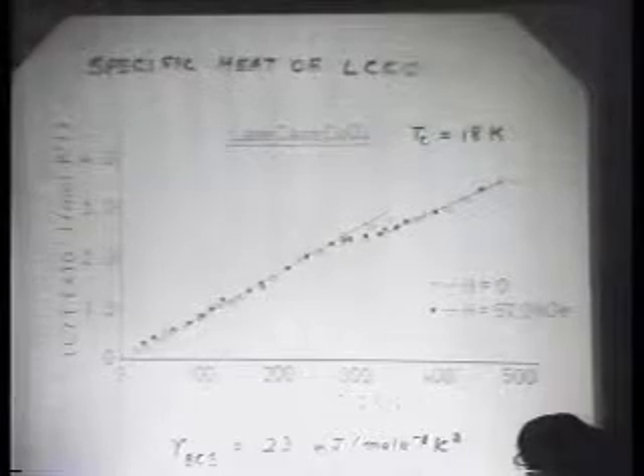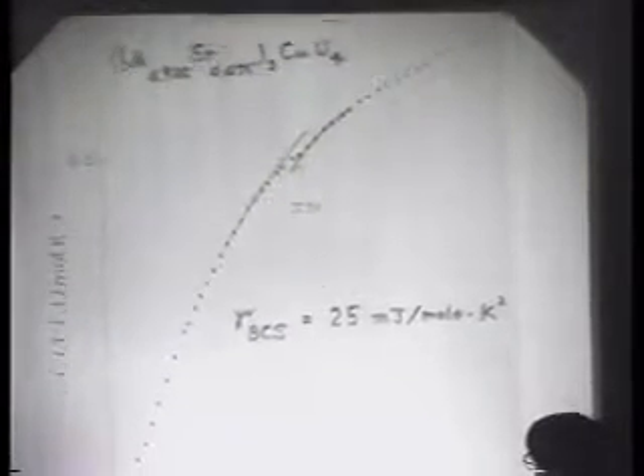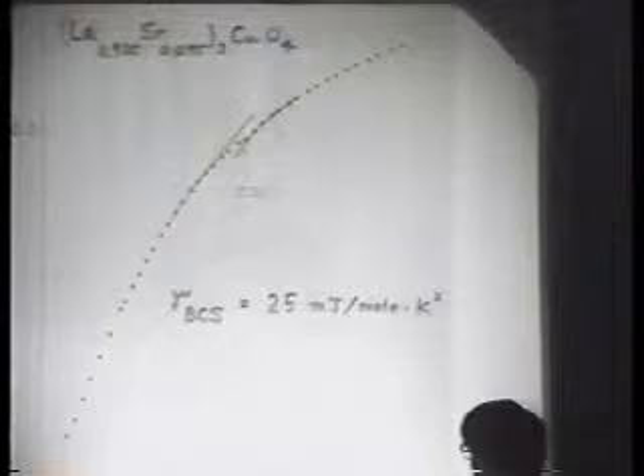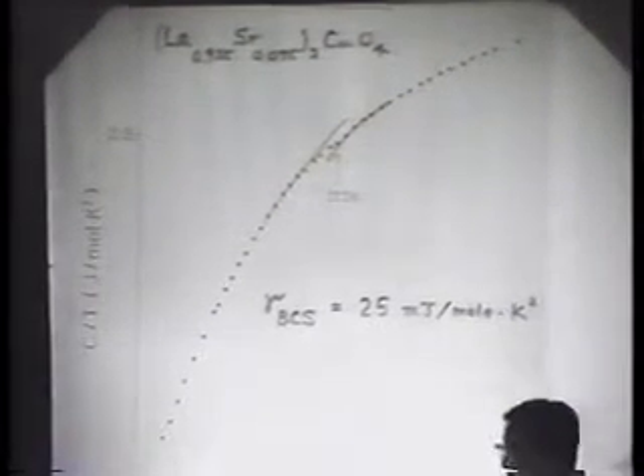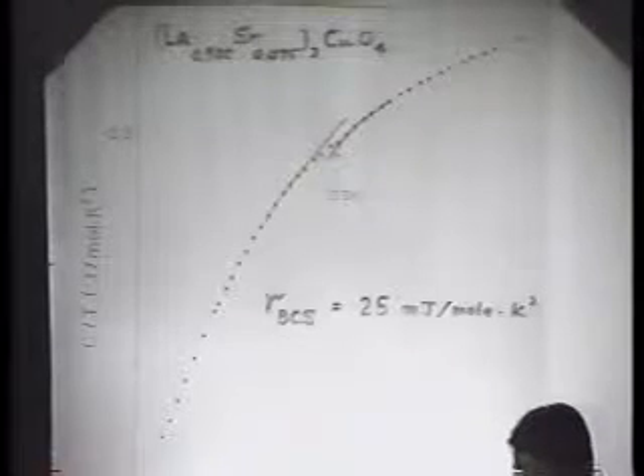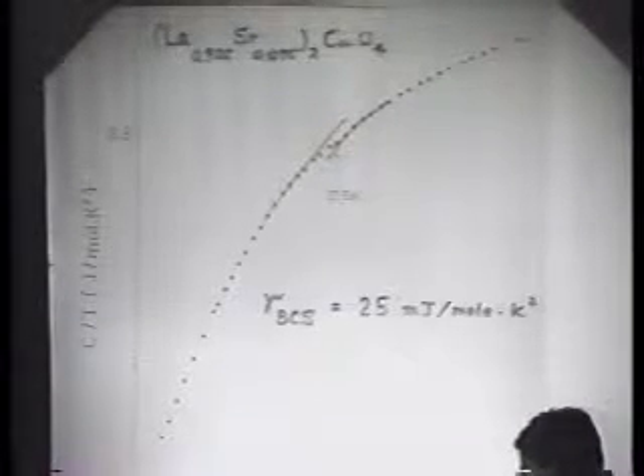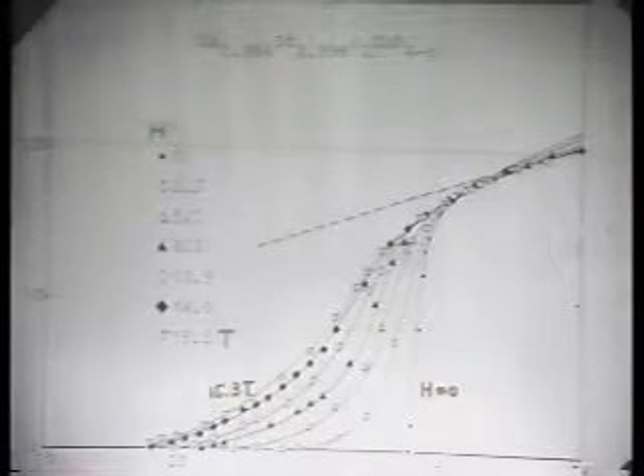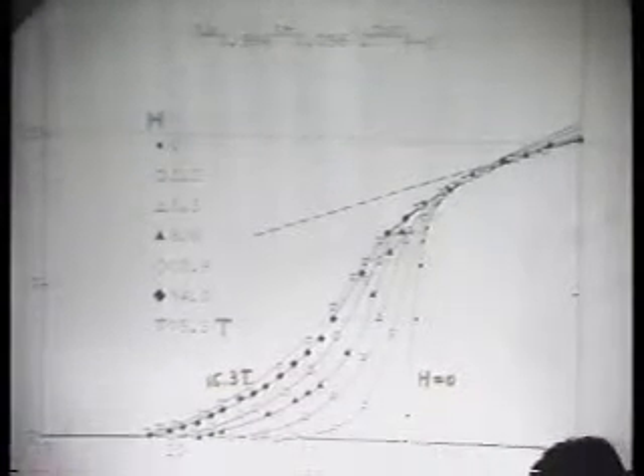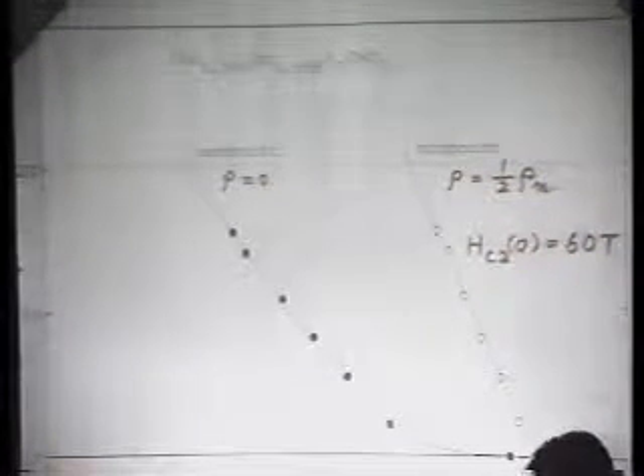This is lanthanum calcium copper O4. The next one is lanthanum strontium copper O4. And gamma BCS is quite large. And the effect of high magnetic field: temperature dependence of the conductivity in the high static magnetic field. HC2 is estimated to be 60 Tesla. Okay, 60 Tesla. Summarizing these data, finally we make a tentative list of normal physical parameters and superconducting parameters.